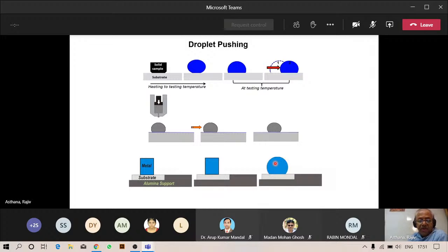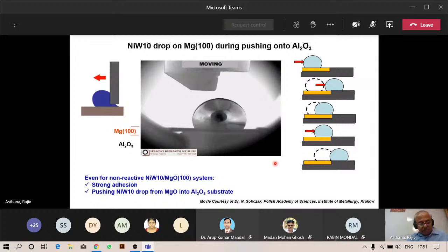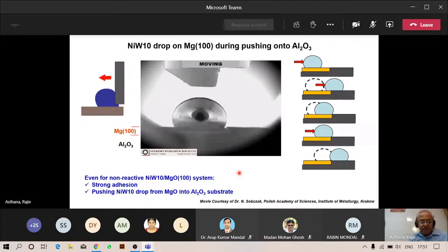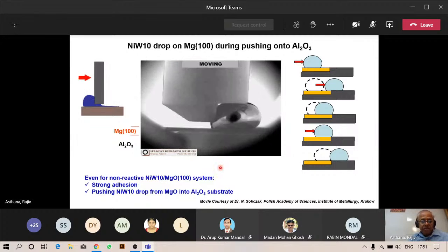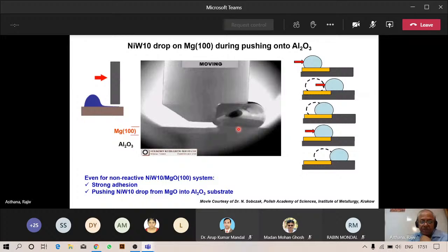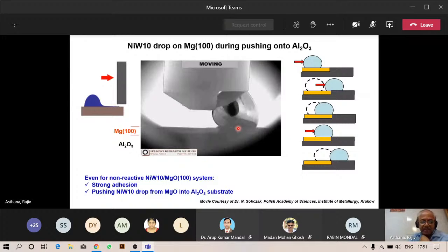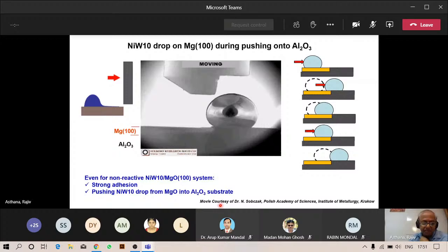So initially, when you push this droplet, let me just repeat this one again. You're pushing this droplet, but it's coming back. There are two things happening here. We have a magnesium oxide, this should be MgO 100, and then underneath you have aluminum oxide. Initially, when you try to push, the droplet wants to come back to magnesium oxide. It doesn't slide up on the aluminum oxide.